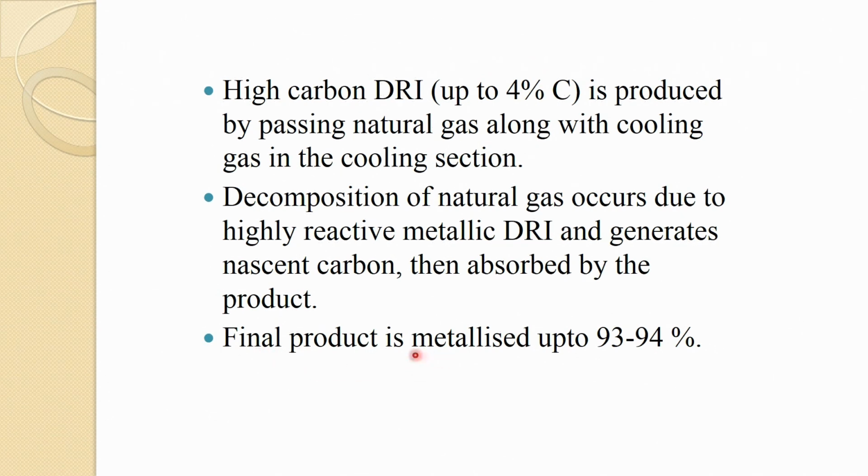So, the final product is metallized up to 93 to 94%. So, a very high degree of metallization.